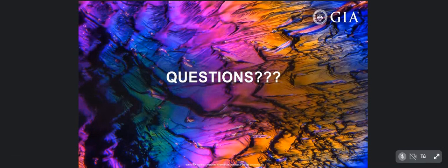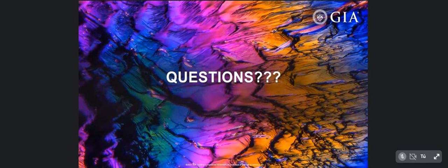Especially the other type of hydrothermal metamorphic emeralds often have three-phase inclusions as well. You can see them in Afghan emeralds, even though the Afghan emeralds tend to have more complex phase compositions. You do sometimes see three-phase inclusions there. There is this small deposit in Musakashi in Zambia, which is different from the main deposit in Zambia, which also produces three-phase inclusions. You can see them in Chinese emeralds sometimes as well.